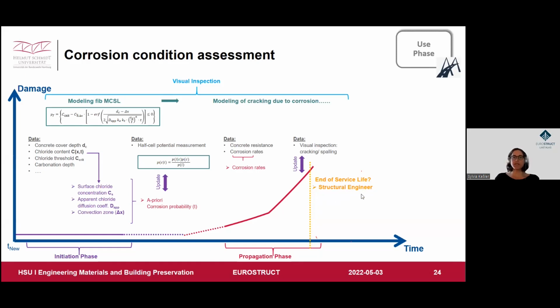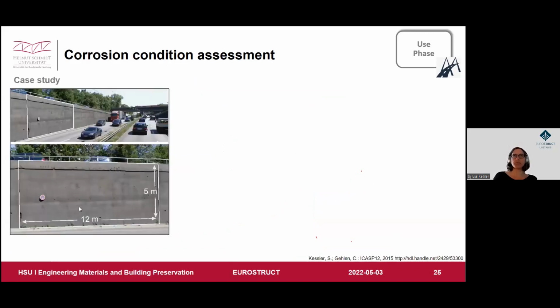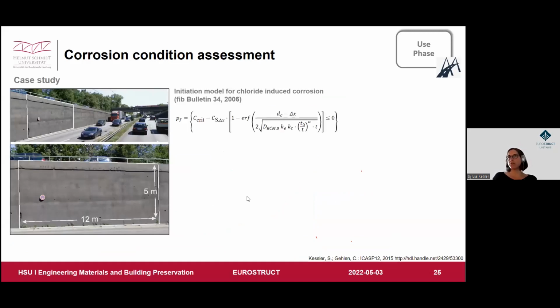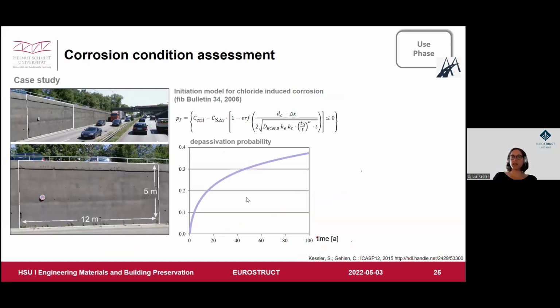Now I want to proceed with a case study where all the overview comes to life. Here I want to come back to my abutment wall, which you have already seen beforehand. As you do at the beginning, you start your probabilistic modeling to get an idea of your a priori depassivation probability. At the time of inspection, the structure was more than 45 years old. Here we have a depassivation probability for this particular structure of 30%, so a corrosion probability of 30%. It's quite high. This was the reason why we decided to do some further inspection.